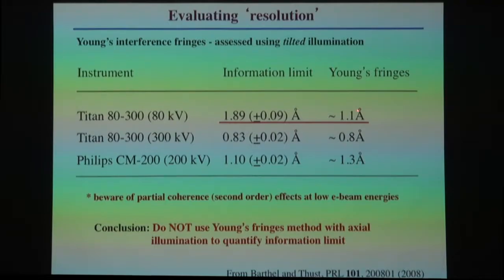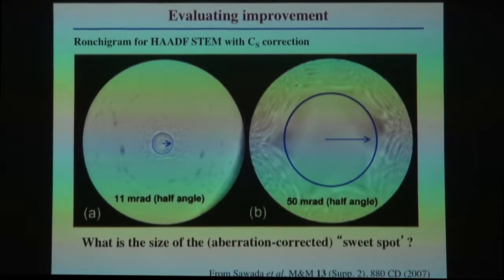Here is the Young's fringes, though, at 80 kV, 1.1 angstrom. Information limit 1.89 angstroms. And so the Young's fringes method may give you the wrong value. So you have to be careful. It's what is called partial coherence, and you should not use the Young's fringes method with axial illumination if you want to know how good your microscope is.